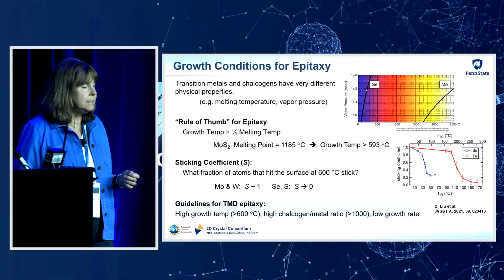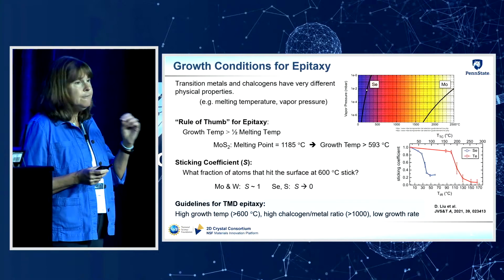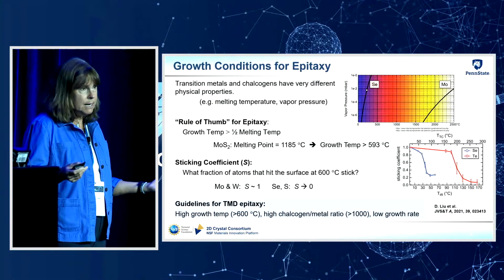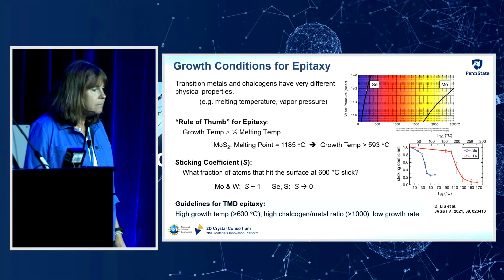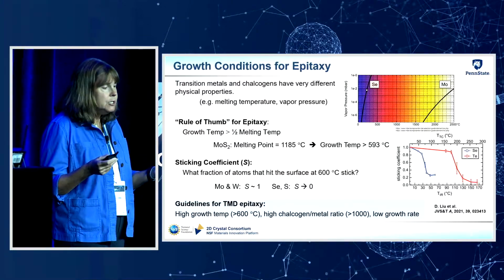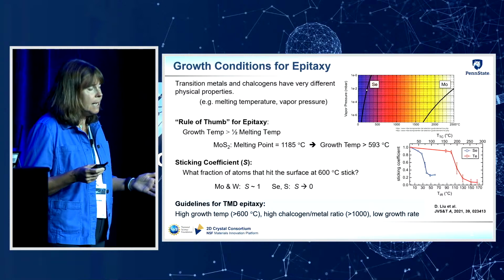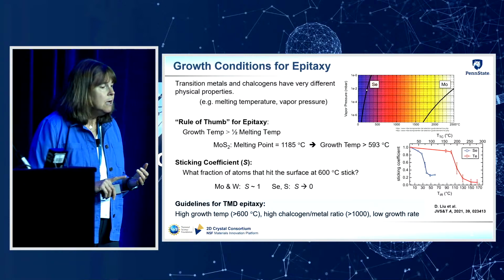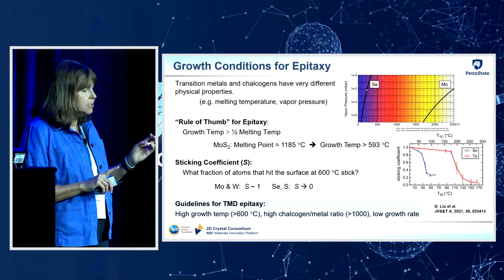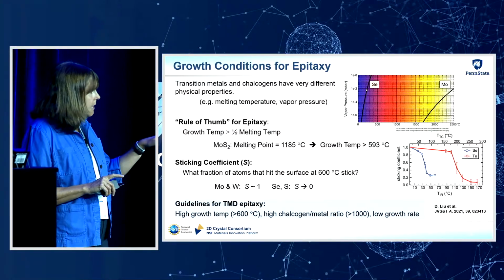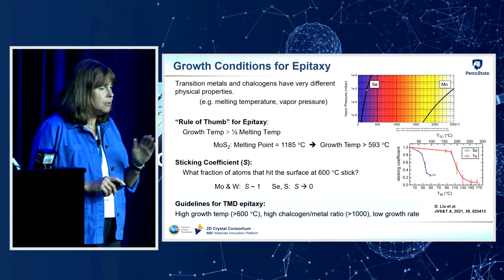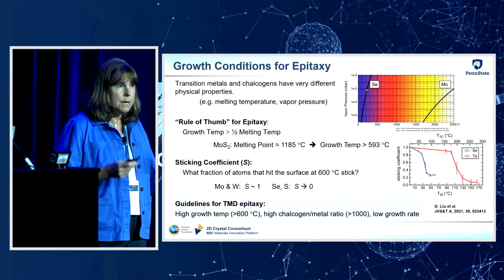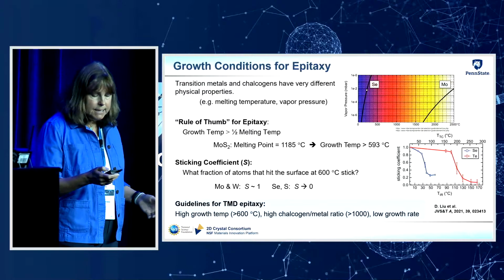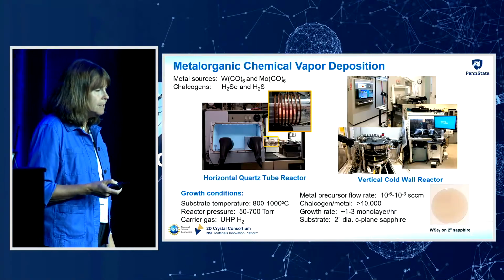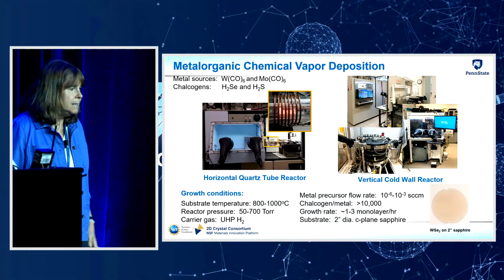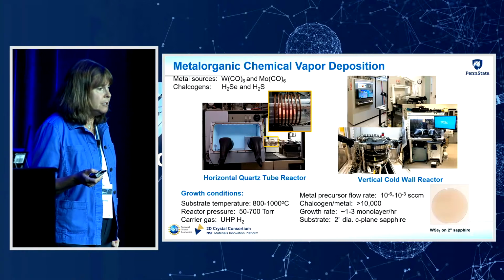And there have been some measurements done in the literature as shown here. They have very low sticking coefficients, particularly at a temperature of like 600 degrees C. So these kind of set the conditions that we need to use for TMD epitaxy. We need to use high growth temperatures. We need to have a great excess of chalcogen compared to our metal, just to have enough of the chalcogen around to get stoichiometric growth. And then we also want to grow at a low growth rate so that we're just depositing a single monolayer on our substrate surface. So the technique that we use at Penn State is metal organic chemical vapor deposition.